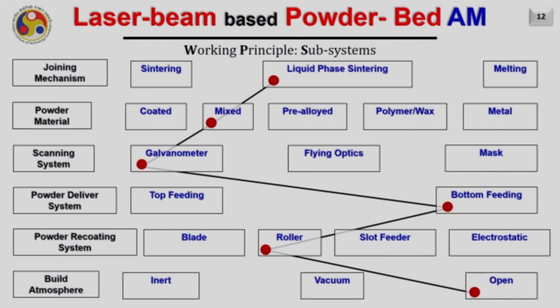Then after that we come to direct selective laser sintering, where liquid phase sintering is the main mechanism for joining the layers. Usually a mixed powder material is used. A galvanometer is used to scan the laser beam over the powder bed. Bottom feeding is used to deliver the material, and a roller is used to spread the powder particles onto the powder bed. And then an open environment is used in the machine. Another variant could be where liquid phase sintering is used with pre-alloyed powder particles, a galvanometer is used to scan the top layer of the powder bed, bottom feeding is used to make the powder available for depositing onto the powder bed, and then rollers or blades are used to spread the layer, and the whole thing is happening in an open environment.